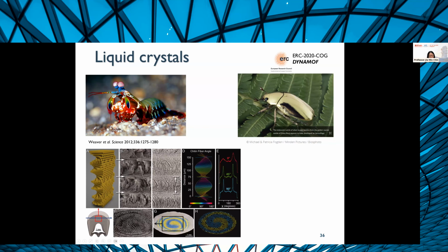And the reason it can do this is because it has this very complex architecture, which is kind of like a cholesteric or chiral liquid crystal. So it kind of grows like this. It's thought that these structures create this very beautiful architecture, starting from chitin and different proteins, well, primarily chitin, that is then biomineralized. So the chitin self-assembles into liquid crystalline structures that are then mineralized, and this allows architectures which are very, very good at dissipating impact energy. You also have these scarab beetles, which have similar types of architecture, very complex, and they can reflect circularly